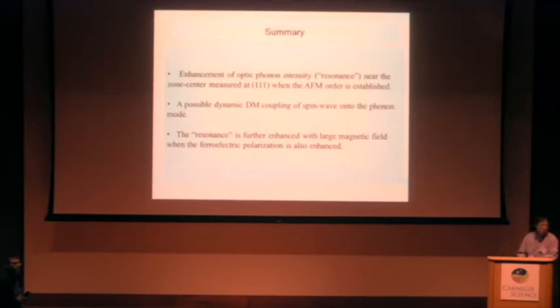When you have a large temperature, the phonons that become more important for the vibrational or thermodynamic properties of the system are high energy. So it's on those that you could probably see larger effects from the magnetic disorder. If you look into the low energy phonons, even if you go high in temperature, you probably wouldn't see anything there, because they are not really coming into play.